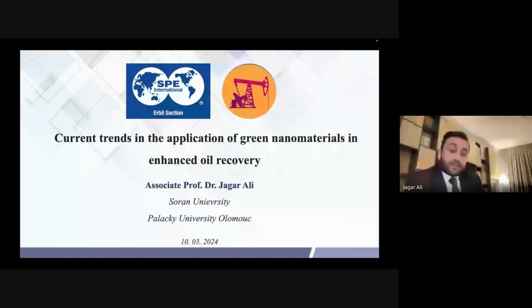So about pH, yes, it affects. So it should be adjusted. For example, if you want to prepare nanoparticles, you should keep it above 10. Then you will have nanoparticles. When you want to have nanotubes, there are other standards to do it. And when you do that, for example, you will add some salts to the solution, and continuously you should monitor the pH, because if the pH is changed, that means the reaction condition will be changed, and then you will not get what you want.